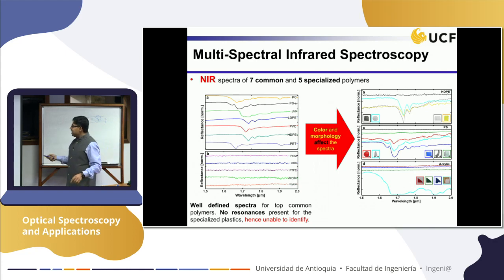But now the problem is that as soon as you do so, and you see I'm actually looking at the same HDPE, just yellow and gray color, and two completely different spectra. In the same way, if I'm looking through a polystyrene, just based on color, whether it's red or green or gray, the spectrum could be different, or acrylic. So based on the colorant, the plastic remains the same, but I'm adding a colorant and its spectral response changes. So that makes my life even harder.